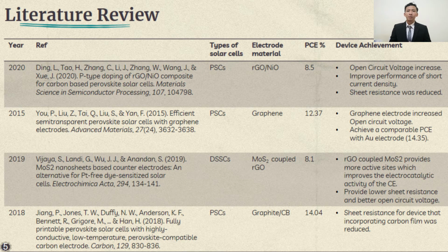Based on previous studies, I have summarized some of the journals that are related to this research. From the results, we can see that the use of carbon-based materials is proven effective in improving the performance of the solar cells, as they manage to obtain a good power conversion efficiency comparable to metal electrodes. Based on the achievements, we can see that the open circuit voltage is increasing while the sheet resistance is reducing. This literature provides good support to further my research objective. Based on previous reports also, RGO MoS2 composite is not yet integrated as the top electrode in perovskite solar cells. Hence, this study could be novel in this niche.